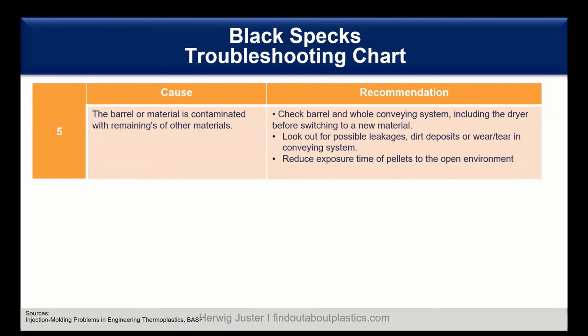Also look out for possible leakages, also dirt deposits or wear and tear in the conveying system itself, which can cause some black specks, or it can also be that some metal material gets split off the barrel. And in general, reduce the exposure time of pellets to the open environment. So look to process as clean as possible, to not get any dust or anything into your whole system.